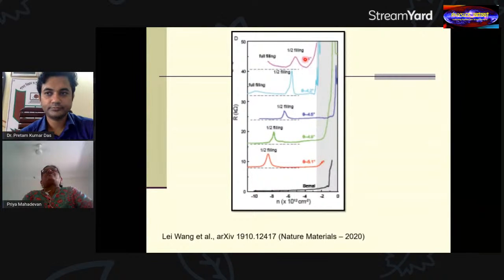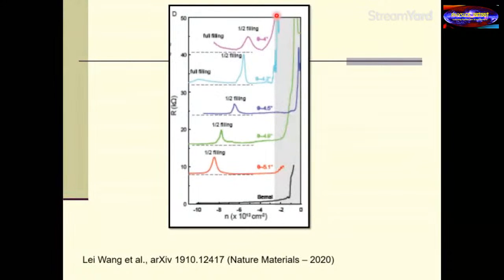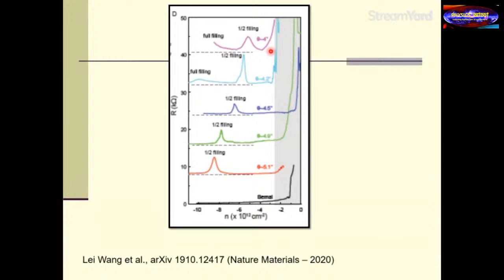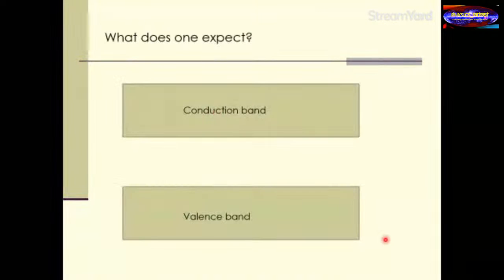Well, but when you look at different structures, different angles of rotation that have been considered over here, what you can see in these cases is that there's something more which is emerging. You have this same behavior in the almost semiconducting region. You have this high rise, and then you come down, and then it becomes metallic, and then again its resistivity increases, almost as if again it's becoming a semiconductor, and then again becomes metallic. You're seeing that as a function of doping, it's a semiconductor, a metal, and then a semiconductor, and again back to metallic properties, which seem very, very surprising to expect.